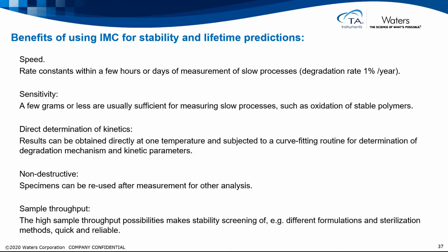So the benefits of using microcalorimetry for stability in lifetime prediction is speed. You can get rate constants within a few hours or maybe days for slow processes. Sensitivity, it's not very much sample that is needed. We get a direct determination of kinetics. It's non-destructive. Samples can be further analyzed afterwards. And the sample throughput. 48 simultaneous measurements is possible, so screening of different formulations and sterilization methods can be done quickly and reliably.